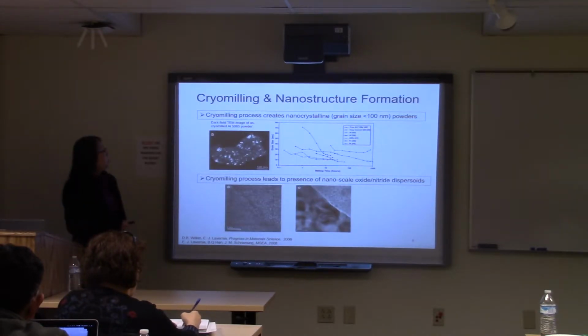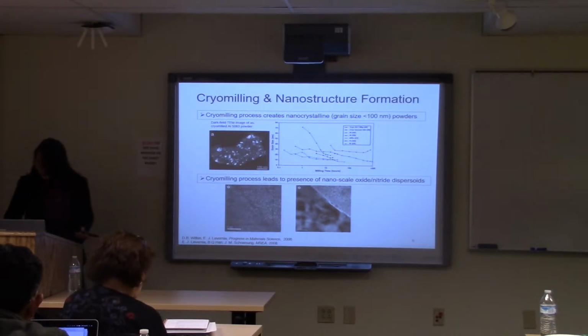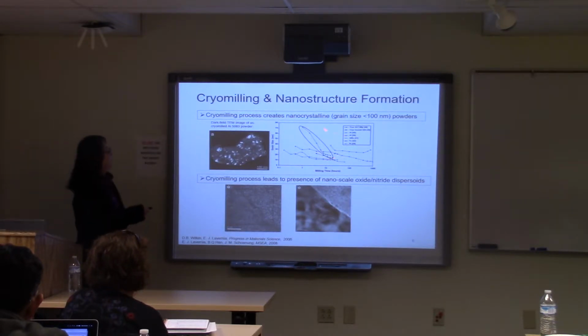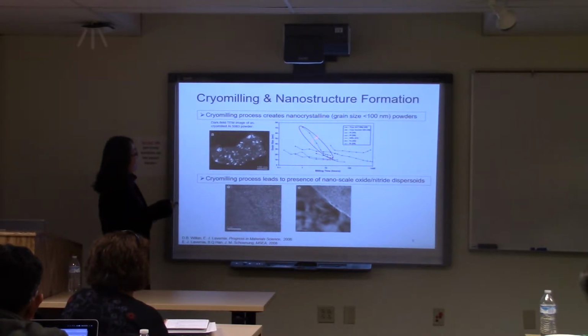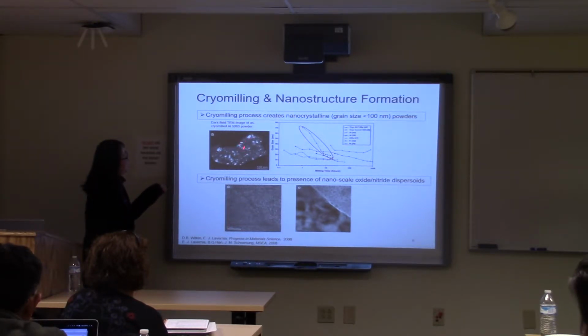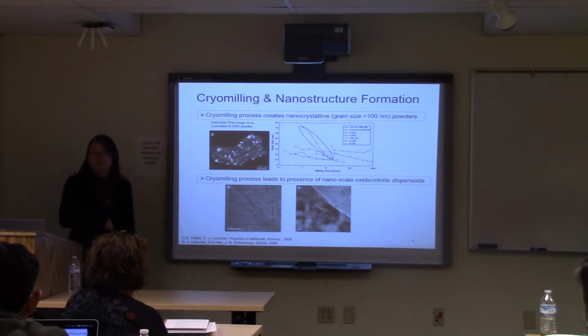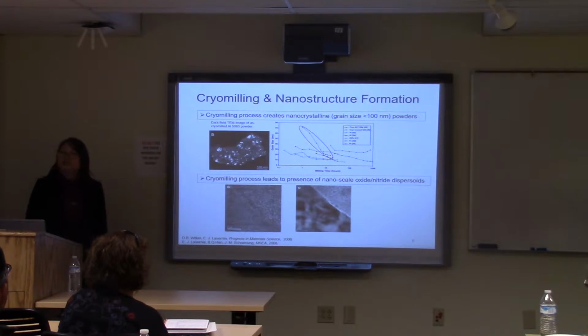Previous work from my advisor's group showed that cryomilling can generate narrow size distribution particles. This is a TEM, transmission electron microscopy, image showing grains about 20 nanometers in size. Within 12 hours, you can already generate a powder with such a narrow size.